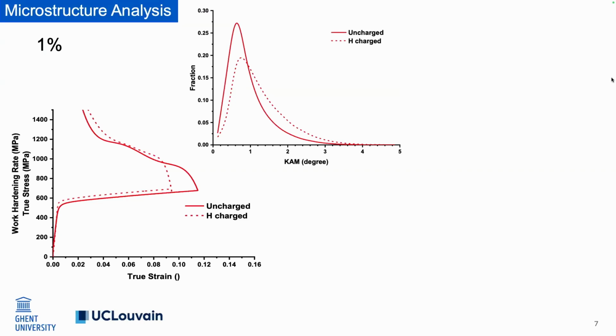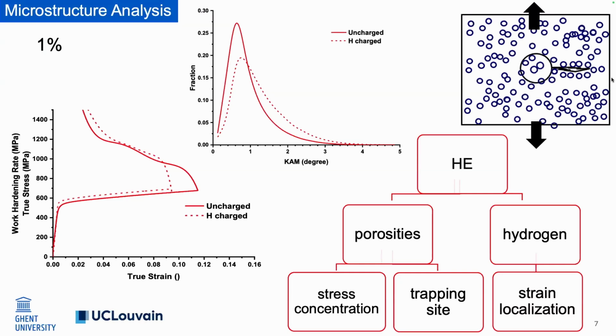But the point is that the KAM intensity distribution shows that hydrogen charging causes an inhomogeneous strain distribution and dislocation density compared with the uncharged condition. So we can conclude that here porosities act like stress concentration sites, and hydrogen can be trapped inside the pores or at the interface of them with the matrix, and accelerates the hydrogen embrittlement. And hydrogen can trigger this process via strain localization in the microstructure.